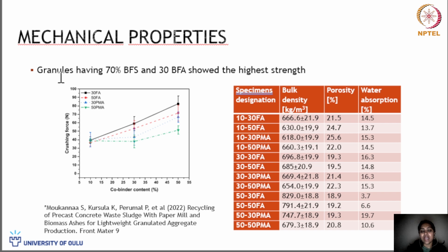So you see, this 10, 30 and 50 are co-binder content, right? So the granules with 70% blast furnace slag and 30% of fly ash perform better with the strength property. This is co-binder, meaning the percentage of different co-binders in the total amount of co-binder. So anyway, 50% of recycled concrete fines from the precast industry with 50% of co-binder, and in the 50%, 70% is slag and 30% is biomass fly ash.